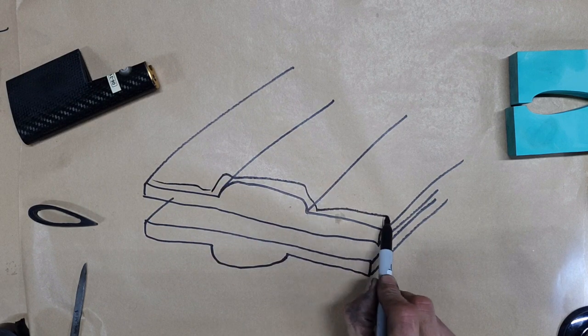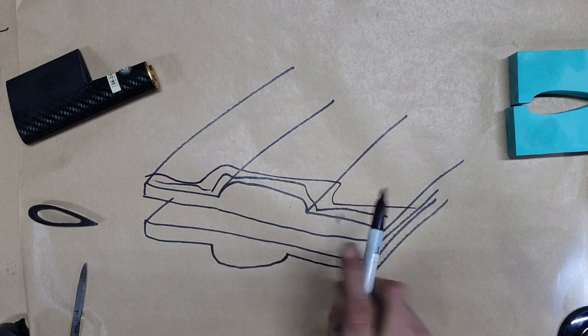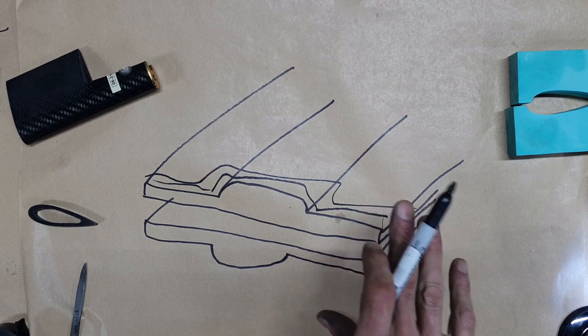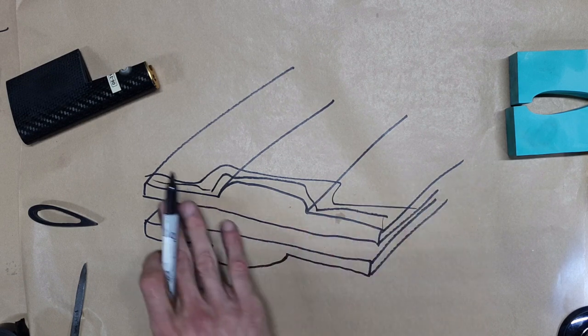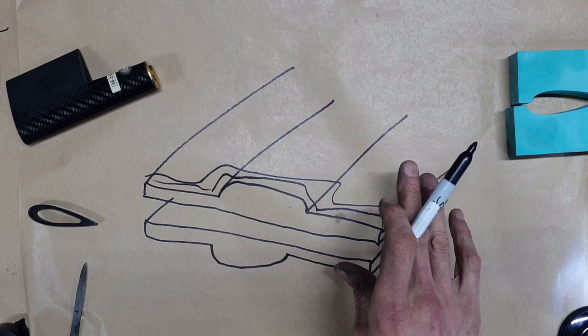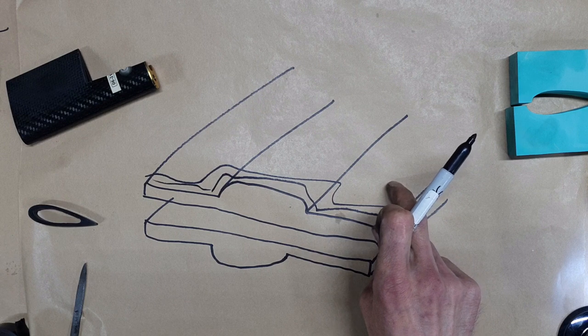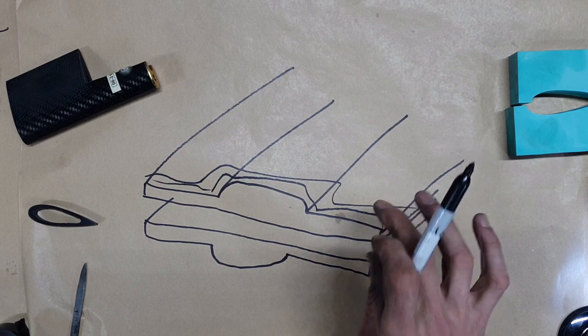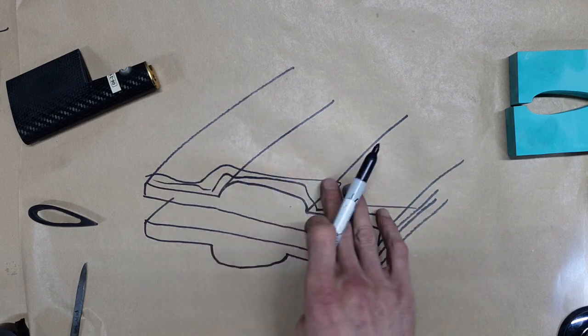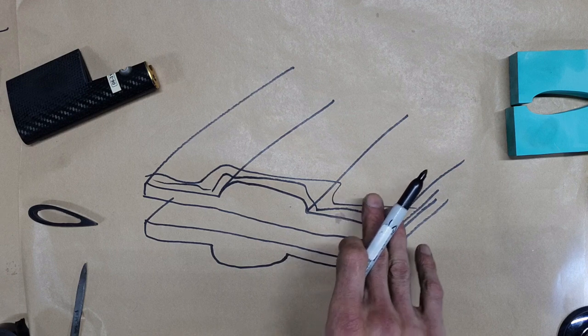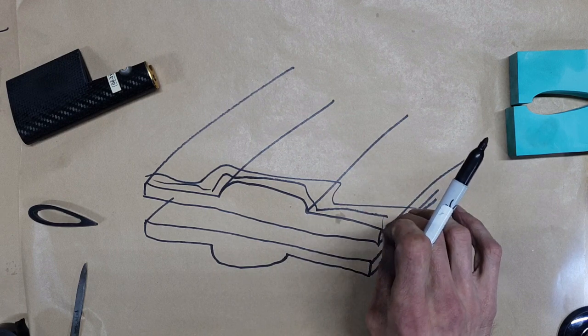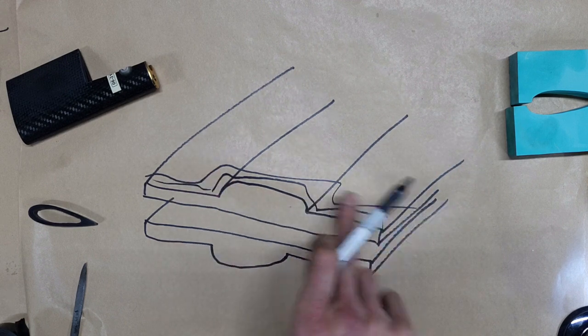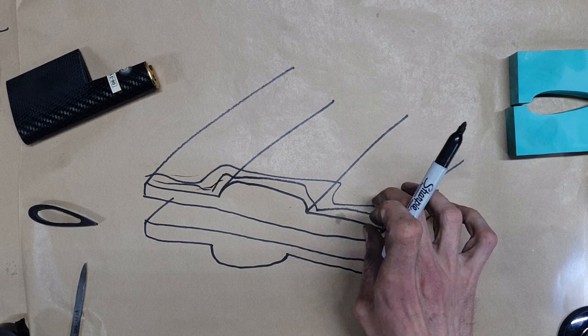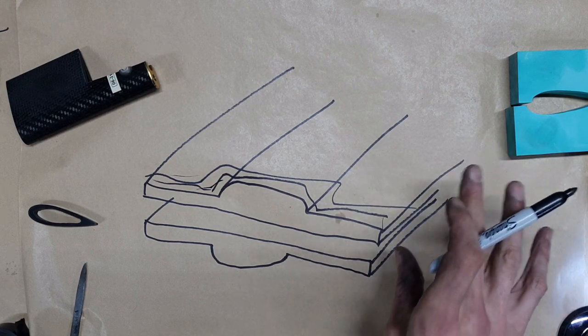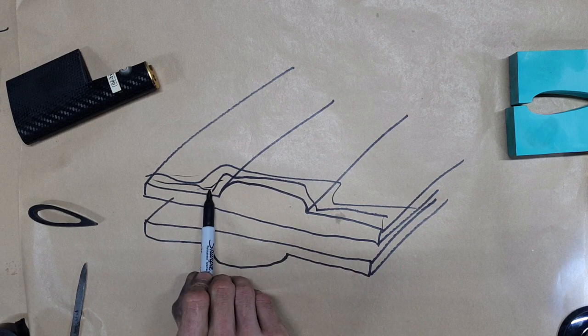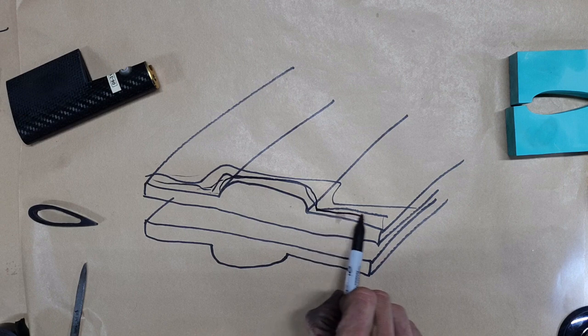pre-preg on here. So many layers again of just a non-cosmetic, non-functional pre-preg tooling carbon fiber, lay it on there. If you're laying up carbon fiber, you have to do what's called a debulk, which would be compressing the fibers or the layers down as you go. So you would lay up a maximum of 5 layers, debulk it with a vacuum bag so that they all squeeze down, pack tight together, lay up more layers, debulk that again, and then put in the autoclave under vacuum. So the debulk just gets them all to conform tightly as you go onto the tooling shape.